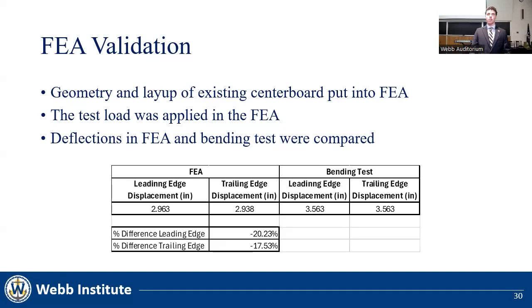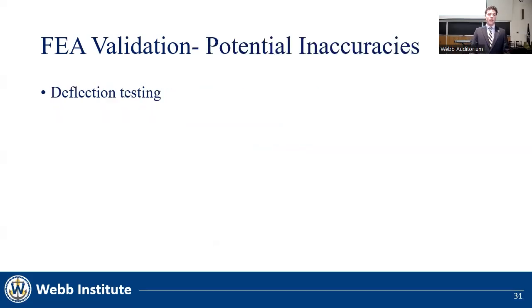At the leading edge, this represents a difference of about 20%, with the FEA underpredicting the bending test results. At the trailing edge, the deflection is also underpredicted, but only by 17.5%. Potential inaccuracies in our FEA validation could result from inaccuracies in our deflection testing. We noticed at one point in the deflection testing that the table was having a tendency to lift some of its legs off the ground.